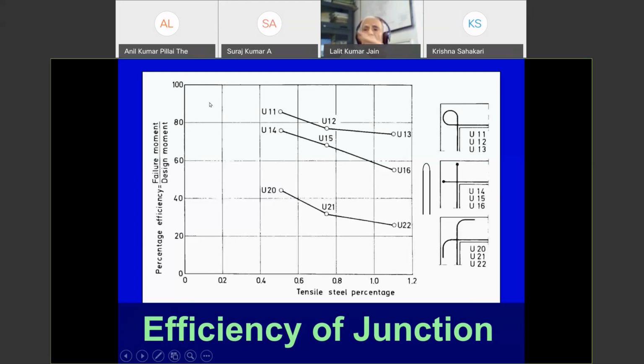And if we see, of course I'm not showing you slides, what happens to crack widths. Crack widths don't increase 10-20% here and there. Crack width just doubles. So crack width is more important. We should do a detailing where the joint efficiency is 100%. We say the joint should be more reliable than the member. Why 100%? As a designer, I think more than 105, 110%. I should have a little extra margin.